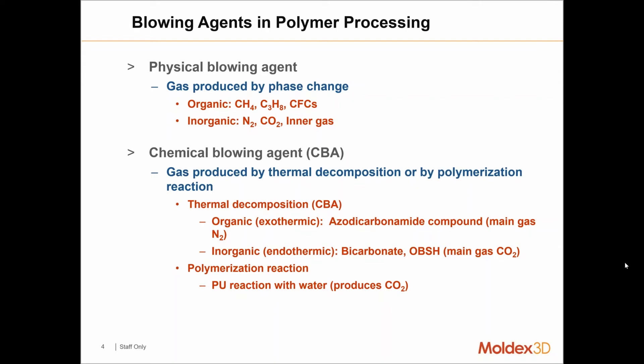For those of you who might not have a lot of experience with foam molding, it's important to understand that there are some fundamentally different processes here. For the physical blowing process, commonly known as mu cell — mu cell is the trade name trademarked by the company Trexel in Massachusetts — this process is more akin to a can of soda. You're actually dissolving nitrogen gas, or perhaps even CO2 gas, into the molten plastic inside of your injection unit.